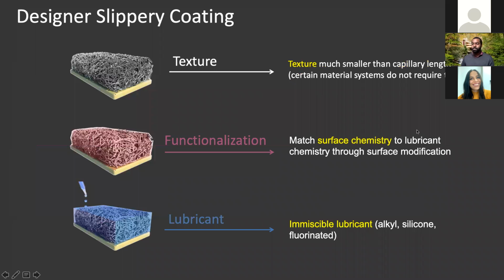So some basic design tips that we're at right now: if we have some texture, the smaller the capillary force, we're able to change the wetting properties to go more extreme in whichever direction. If we control the surface chemistry, this functionalization, then we can change the wetting, the contact angle of these systems. So if you go from, say, something like Teflon, maybe in your nonstick pans, to something that is hydroxyl terminated, then you can drastically change the surface chemistry and the apparent wetting. And if we design it properly, we can have a functionalization that will really trap the lubricant, what I'm going to call this liquid layer, and will really repel whatever it is that we're trying to repel. So having all three of these can really help us design a stable surface.